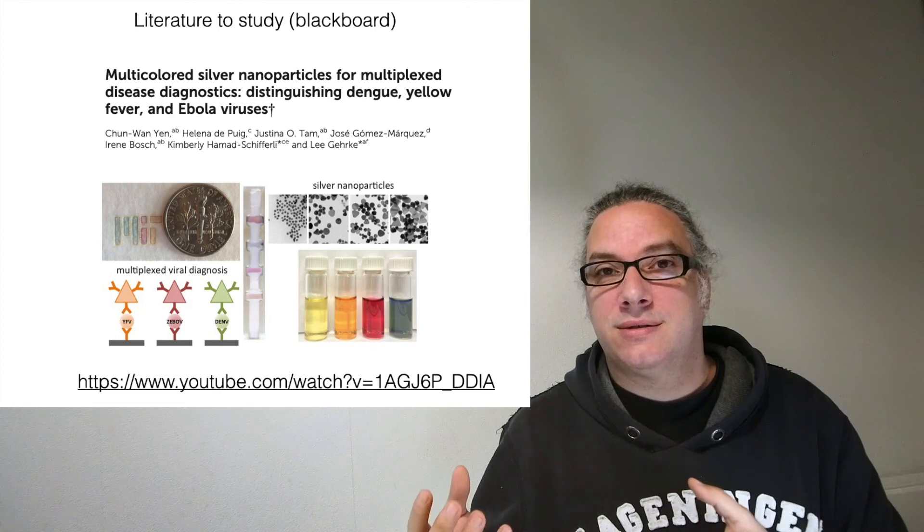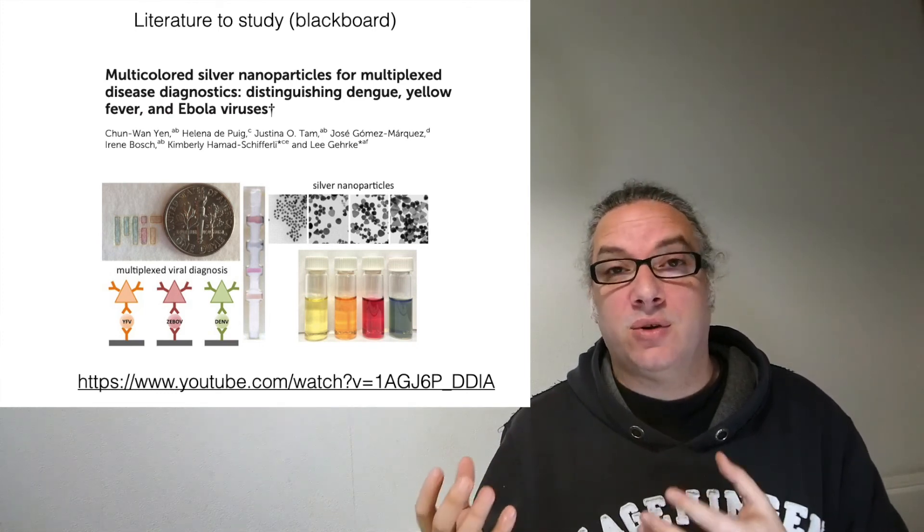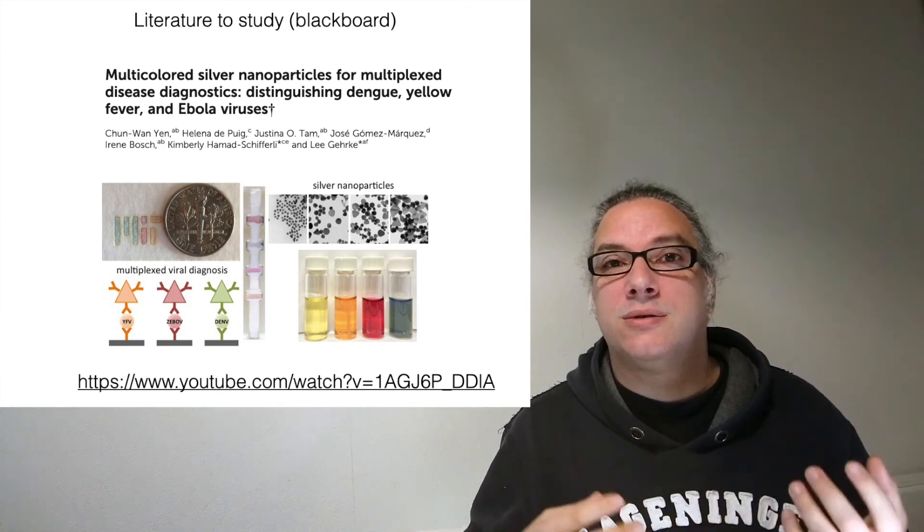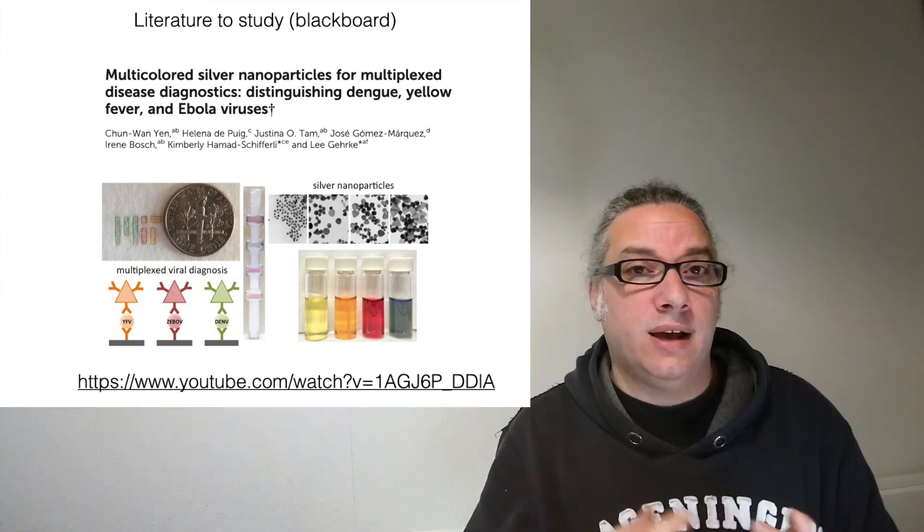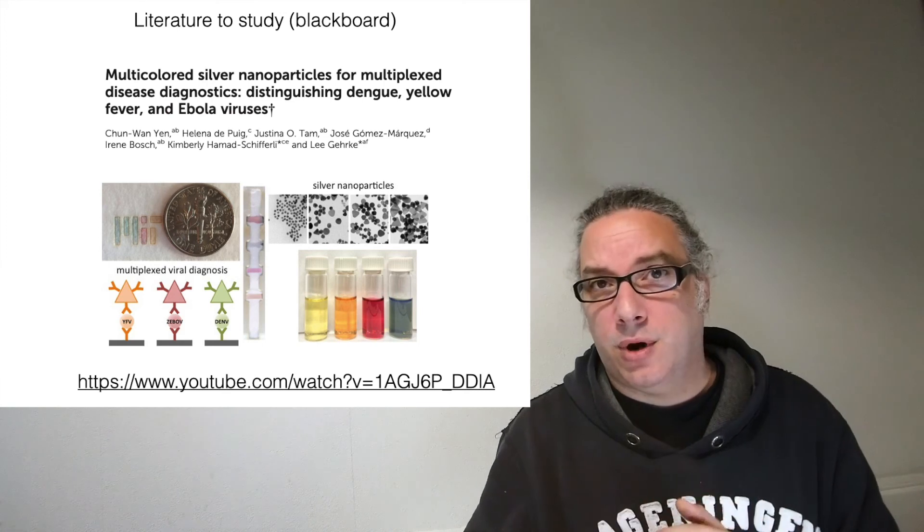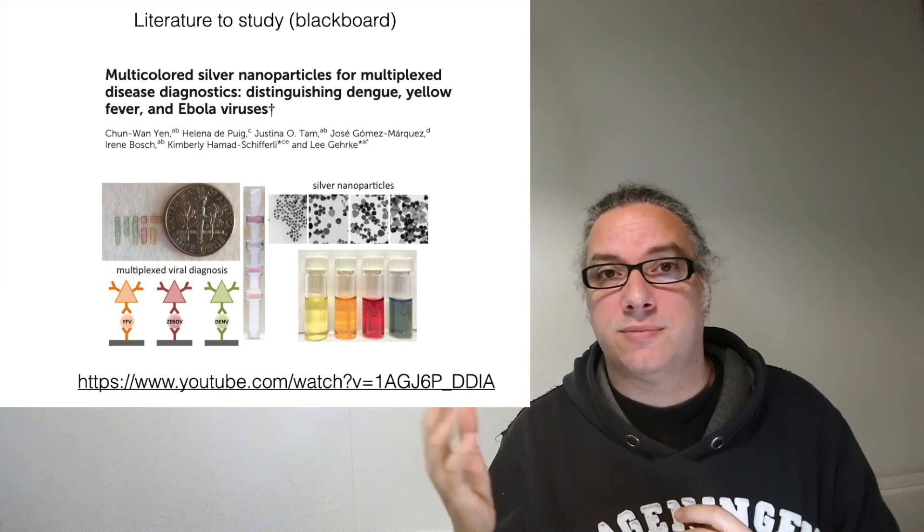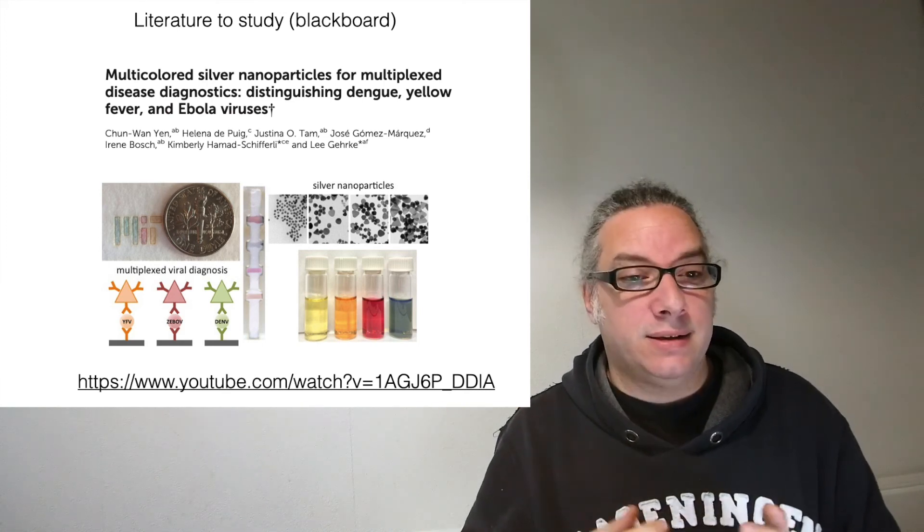The material of the nanoparticle is the same, but you have different colors just because the nanoparticles are different sizes. In a few minutes they can detect dengue, yellow fever, and Ebola on a single strip of paper that costs probably less than 20 cents. I think it's pretty impressive.